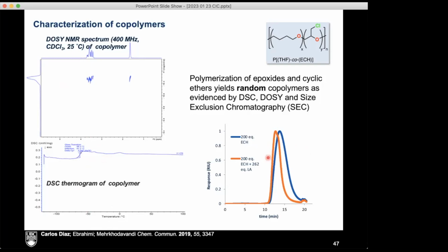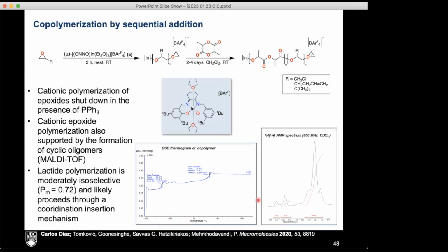So then what Carlos did was change the nature of the catalyst. What he was able to do is just subtly change this. So he changed it from the hexafluoroantimonate to BARF. So change the nature of the anion, and now you have a very large anion. Hexafluoroantimonate is large, but perfluorotetraphenylborate is really large. And so in this case, what he was able to do is something quite different. He was able to actually carry out the block copolymerization of epoxide and lactide.